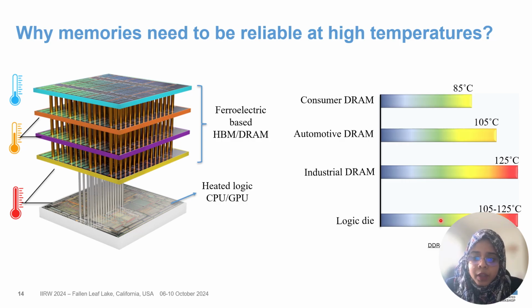And if we look into the DRAM qualification temperatures, those are 85 to 125 degrees Celsius, depending on its application. But DRAMs don't like heat in general, because above 85C, for every 10 degrees Celsius increase in temperature, the refresh rate has to be doubled in DRAM. And the off-current scenario also becomes worse.